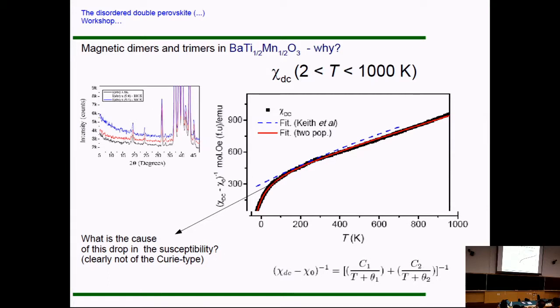And from a phenomenological point of view, we resorted to this two population model. What this model tells us is that you have, say, two populations of spins in your system. At high temperature, you recover the effective moments from manganese 4+ cations, what you actually expect. And at low temperature, apparently you have some spins which are somehow correlated, right?